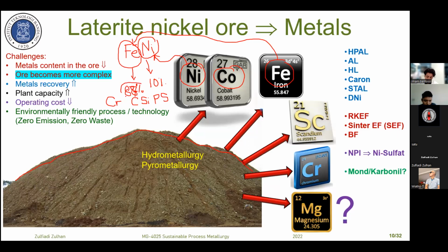So we cannot sell the iron from ferronickel. Nobody will buy it. They just want to buy the nickel. But we extract both together, nickel and iron. Most of the scandium will go to the slag, and most of the chromium also goes to the slag. The recovery of chromium in the metal is less than 5%. And the magnesium, for sure, we cannot reduce magnesium oxide, and calcium oxide will also go directly into the slag.